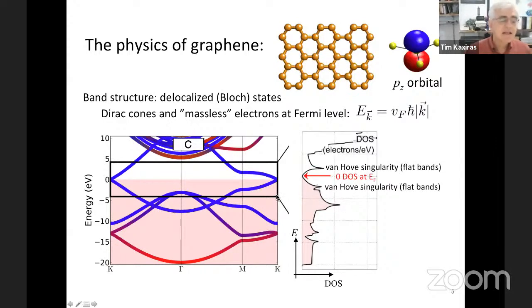The interesting thing is that farther away from the Fermi level, you do see very flat bands. So here are the flat bands in single layer graphene. And early on, many years ago, it was hypothesized that if you can access these flat bands, these Van Hove singularities of the density of states, you could get very interesting behavior in graphene. And it was even hypothesized that graphene could become a superconductor if you could access these states. The problem is that these states are many electron volts, 3 electron volts or so, far from the Fermi level.